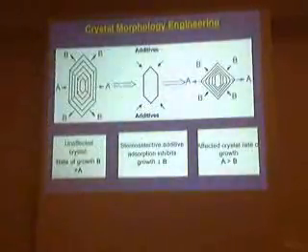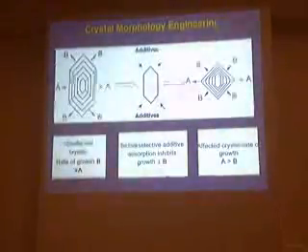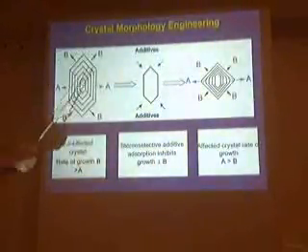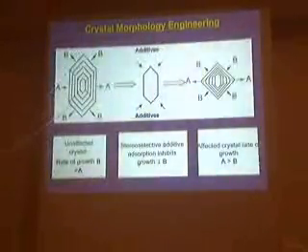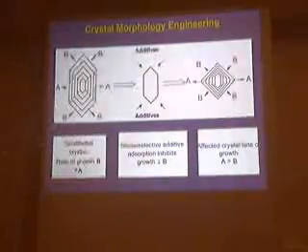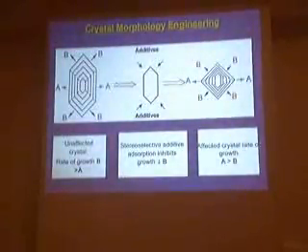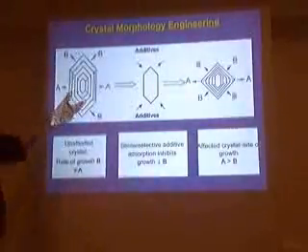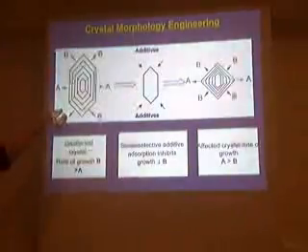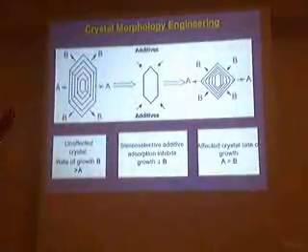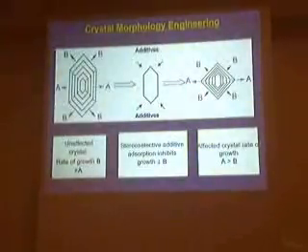And this is now a very general concept, because you can go to any crystal, look at the structures of any of these crystals, see how the phases are composed, and you can now design a molecule which is composed of two parts. One part will bind selectively to some surface, but not to another, and the other part perturbs the growth of this particular surface. And this is very general. We were able to manipulate our crystals as we want.